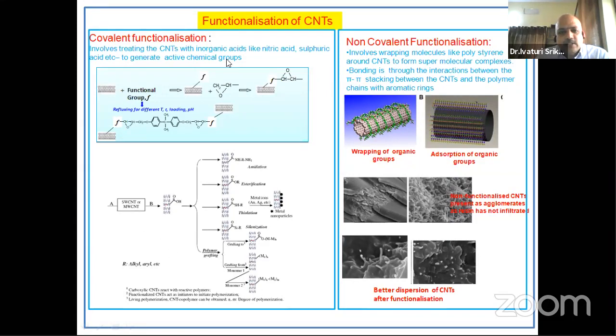Besides this chemical functionalization, what we call, there is another functionalization called non-covalent functionalization. Chemical functionalization is a covalent functionalization. Here the problem is, without functionalization, you will not be able to tap the potential of nanotubes. But when you are functionalizing, wherever you are creating a functional group or a bond, you are breaking the nanotube and introducing a defect. So as you are functionalizing, you are reducing the strength of the nanotube. The very strength of the nanotube is because of its ideal crystalline structure without any defects. Defects are the zones where the failure initiates. So if you don't functionalize, you cannot tap its potential. If you functionalize it, you are reducing its strength.